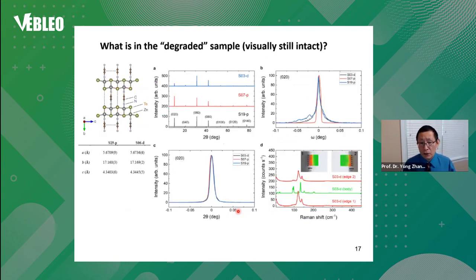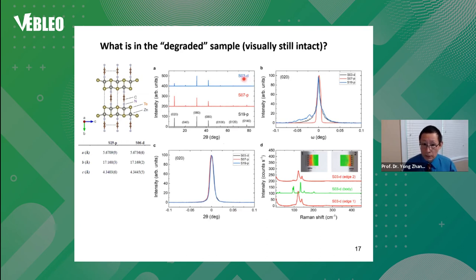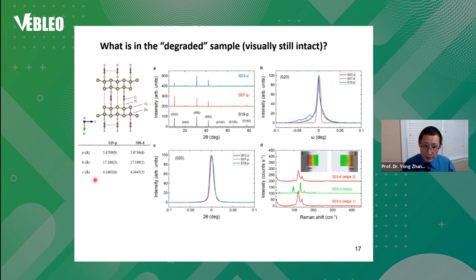What is present in the degraded sample as measured optically? When we did the measurement, the sample still looked just identical to 15 years ago, but the spectroscopic features had changed. We did X-ray measurement on those old and new samples. The XRD peaks along the stacking direction for old and new look very similar, almost identical in terms of relative intensity. And the supposedly severely degraded sample only has a slightly weaker first peak. X-ray analysis shows these two samples have almost identical lattice constants — meaning they are still the same crystal.